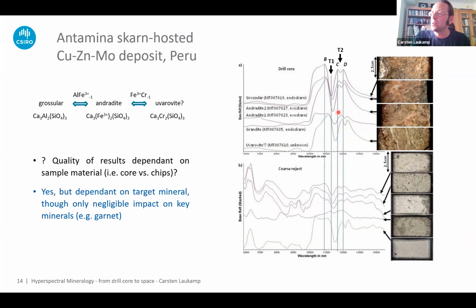But if we're focusing on the main important absorption features for garnets, we see that they're actually pretty much the same, and they're unaffected by volume scattering. So it doesn't matter if I have coarse reject samples or pulp samples or a drill core, I always get my good garnet spectra.